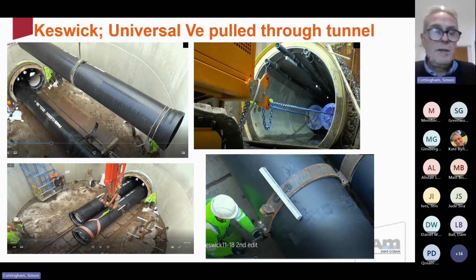This is one example we did up in the northwest, up in Keswick, which was a 280 metre pull of pipes in a tunnel under the River Greta. You can see it was, in this case, a twin pipeline. So we had bespoke carriages that we sat the pipes on that had runners and wheels on the underside so that they were dropped down the shaft. The joint was made at the neck of the tunnel on these spiders, and then the pipe was pulled along till it rested here, and then the next pipes were dropped down and the joint made. So that was a very successful project.